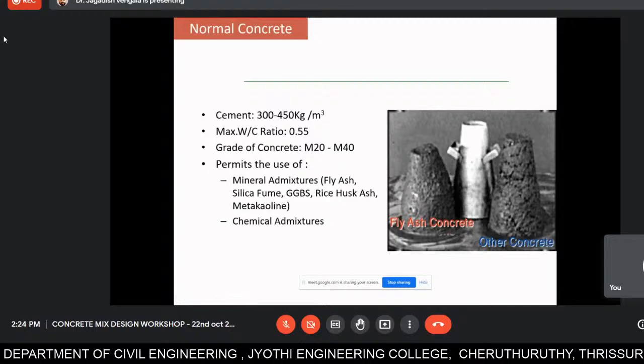So when you look into the table, for the normal concrete, you can see the cement varies between 300 to 450 kg per cubic meter. And the maximum water cement ratio, we start with 0.55 in case of RCC. And the grade of concrete is M20 to M40. Now one can go for M60, M80 nowadays. People are using it at various sites. And IS permits you to use various mineral and chemical admixtures. The most commonly used mineral admixtures nowadays at site are fly ash and GGBS. And in some important cases, to get early strength, people are using silica fume or other mineral admixtures.